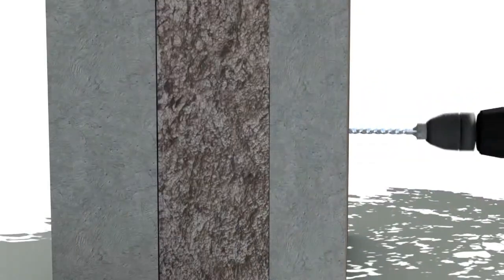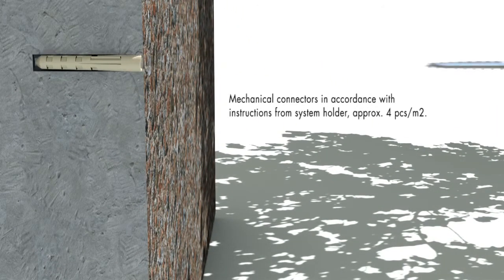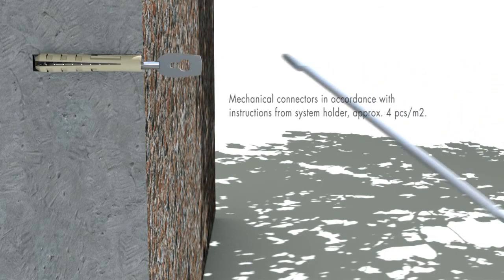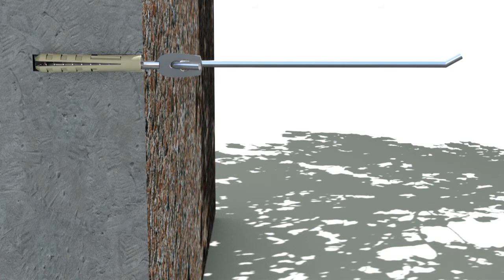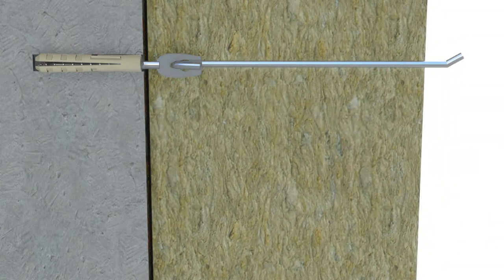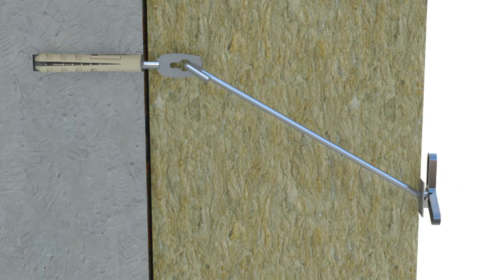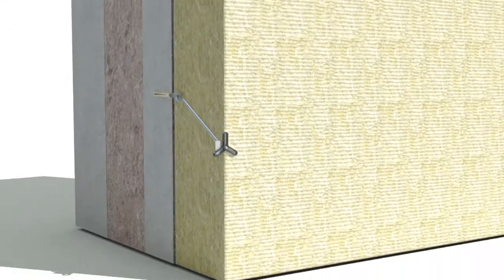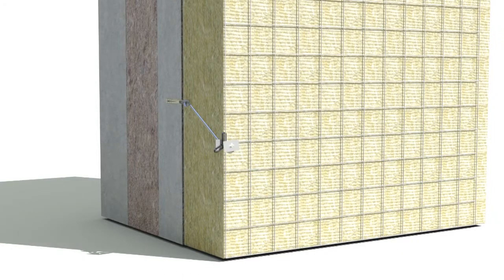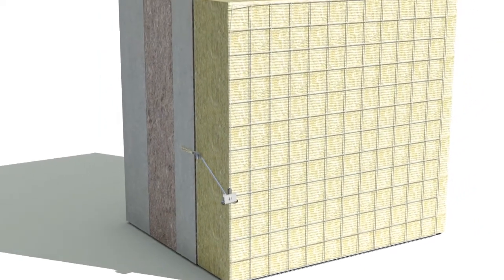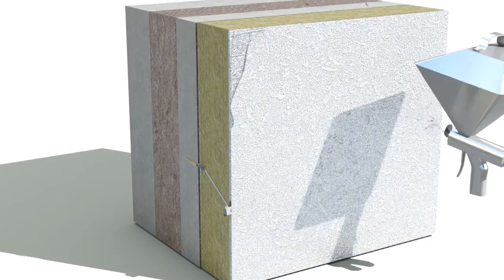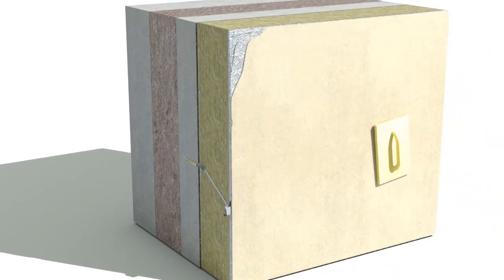Non-ventilated insulated render facade structure. If a condition survey shows that the alignment, strength and adherability of the old structure are sufficient, and if a seamless traditional insulation rendering is selected as the new facade solution, it can be implemented in two different ways. In case of a thick insulation render, select thermal insulation PAROC FAS 1 fixed into the old facade surface by means of mechanical fasteners. A hot rolled steel mesh is fixed to the same mechanical fasteners, and three different layers of render mortar are sprayed onto the mesh in accordance with instructions from the system holder.